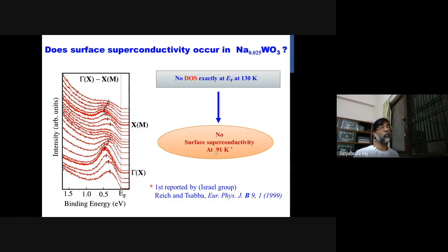And so, because we learned that with a different photon energy you can tune between the bulk and surface electronic structure, we measured at two different photon energies. This spectra we have taken at 130 Kelvin and also at 42 eV, and we didn't see any quasi-particle at EF. So we discard that this claim has any validity of superconductivity. So sodium tungsten bronze is not actually showing any superconductivity.